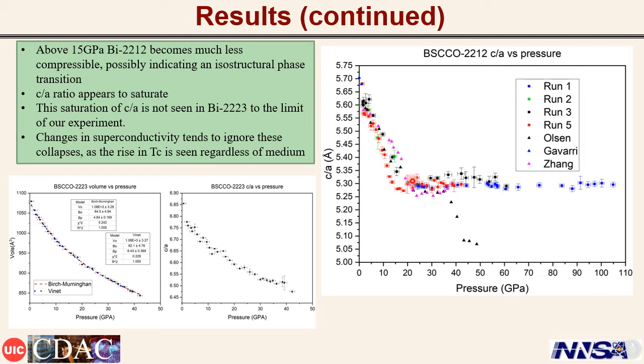In the 3-layer BSCCO samples, a saturation in the C over A parameter was not seen to the limit of the experiment, and a single Vinet equation of state was used to fit the data. We believe that, when placed in a more hydrostatic compression medium, there is no planar collapse in BSCCO 2212. Tc does, however, appear to grow above a critical pressure in all pressure transmitting media, irrespective of hydrostaticity.